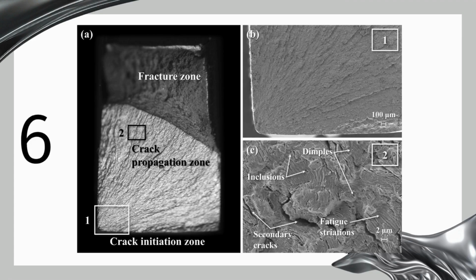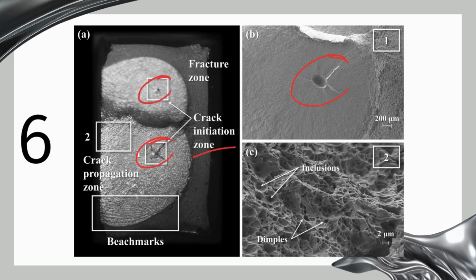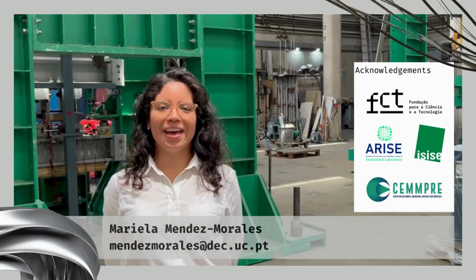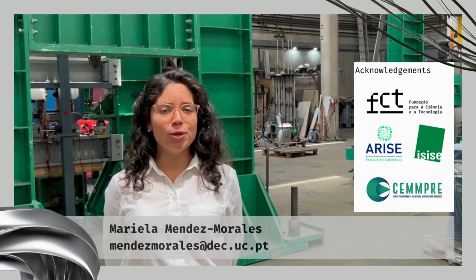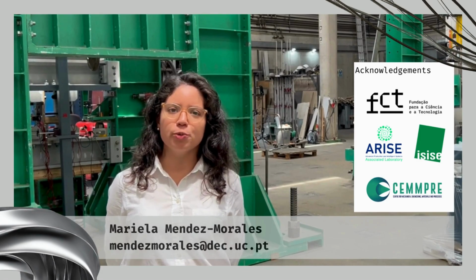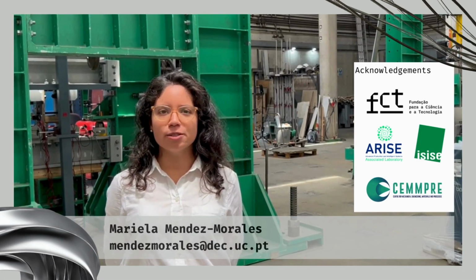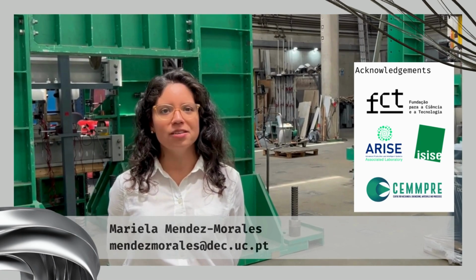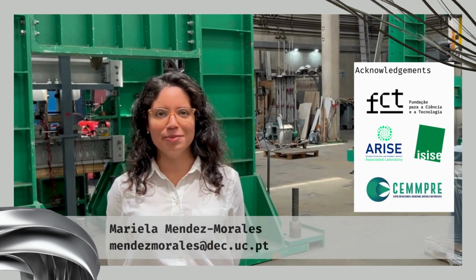SEM analysis of fracture surfaces revealed crack initiation from the surface and from internal defects, likely stemming from trapped gas bubbles during fabrication. In essence, our research not only provides novel design tools for WAAM components, but also highlights the promise of using WAAM carbon steel in fatigue-loaded structural elements.